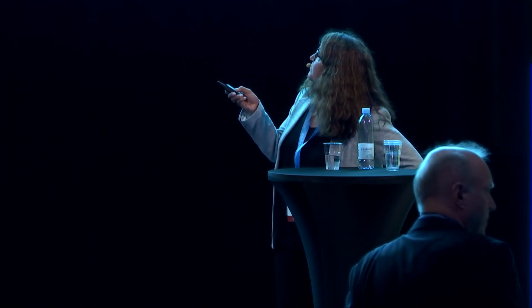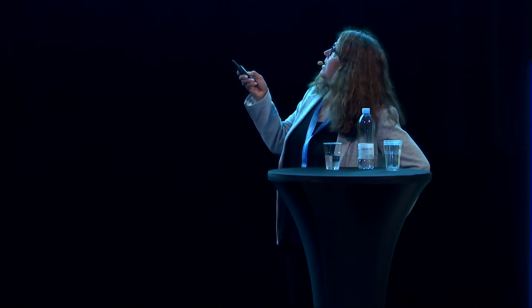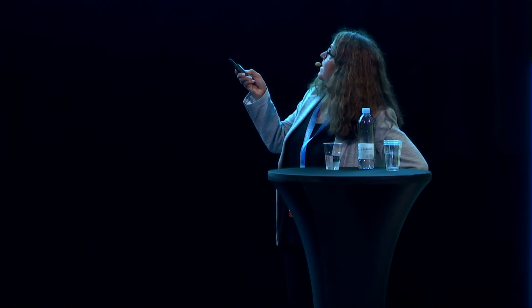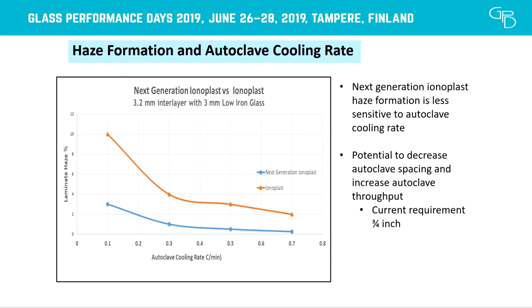This graph shows the effect of cooling rate on haze formation of the new Ionoplast interlayer versus the current Ionoplast interlayer. And you can see here, this is autoclave cooling rate. These are cooling rates that are much slower than what we recommend, which is 2.2. So this is really pushing it to the very slow cooling rate. This is the current Ionoplast, and you can see the haze formation is much more dependent. Just for reference, if this was a stiff PVB or a standard PVB, this line would be completely flat. There would be no dependency whatsoever. So you can see we're starting to get closer to no dependency, but there still is some. Remember, it's a semi-crystalline polymer, so you're going to have some dependency.